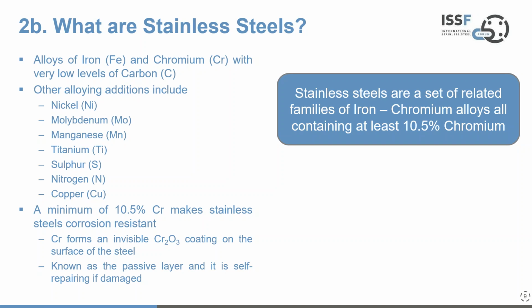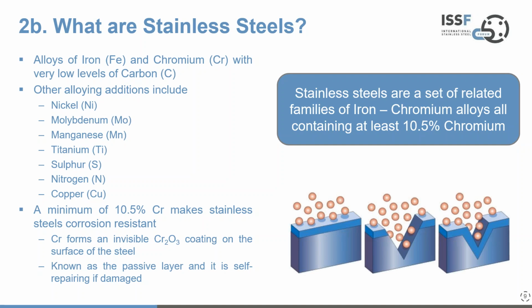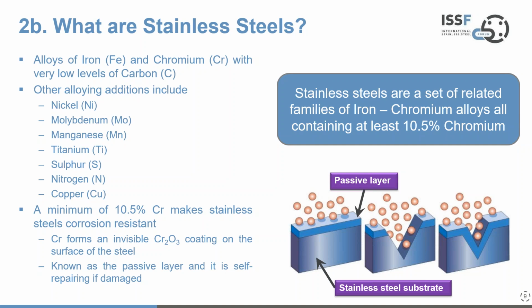And I'd like to try and just demonstrate this with the help of a little diagram. So if you take this diagram that's now appeared on the bottom right-hand corner of your screen, we'll work through the diagram from the left to the right. What you have initially is the stainless steel itself as a substrate material with a layer on top. And that layer is what is known as the passive layer, and it's an invisible chromium oxide coating that forms freely on the surface of all stainless steels in the presence of oxygen. The oxygen atoms are denoted by the little spheres.